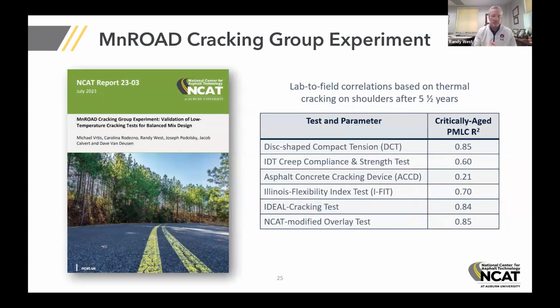Now that's just one experiment, one set of test sections at one location. We had partnered with MnROAD to do a similar experiment in Minnesota, and in Minnesota, the experiment was intended to evaluate thermal cracking or low temperature cracking. I don't want to go through all of the details I went through for the NCAT experiment, but again, we looked at a variety of tests. We looked at the correlation between the lab and field performance, and that experiment is documented in a separate report. And we see there are some tests that did have a good relationship between the lab test and the thermal cracking that we observed in Minnesota after 5.5 years.